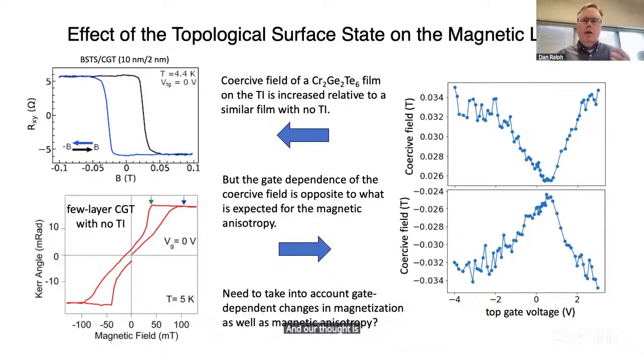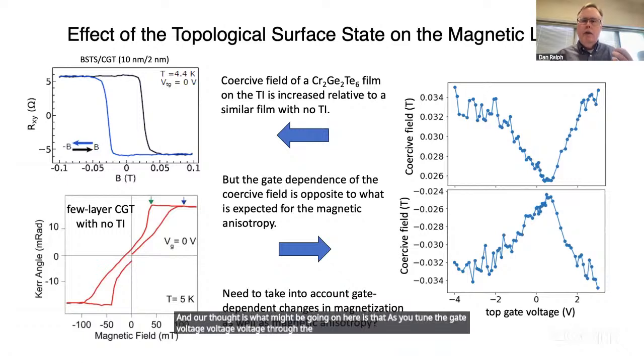So if you think about what determines the coercive field, there's the influence of the magnetic field trying to drive the magnetization parallel to the magnetic field, versus the anisotropy field trying to oppose that. And our thought is what might be going on here is that as you tune the gate voltage through the exchange gap, you're changing what the magnetization of the surface state is, as well as changing what the anisotropy of the magnetic